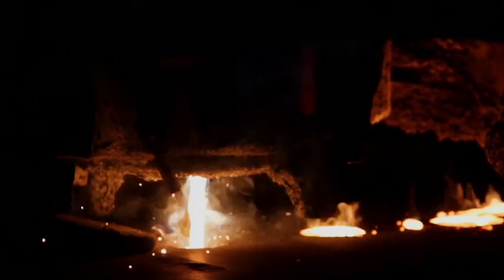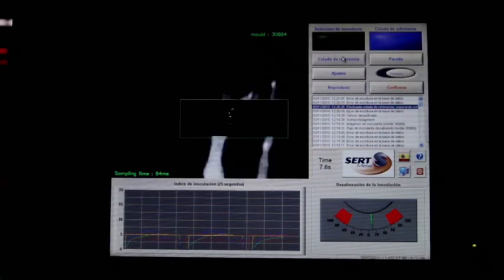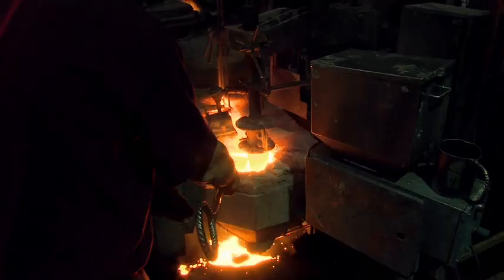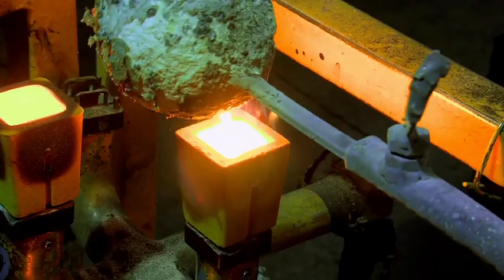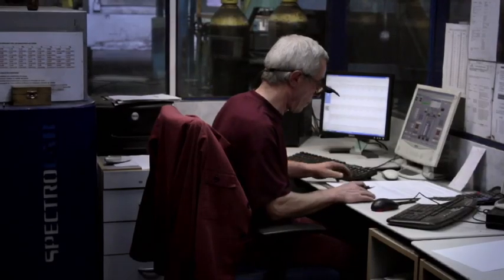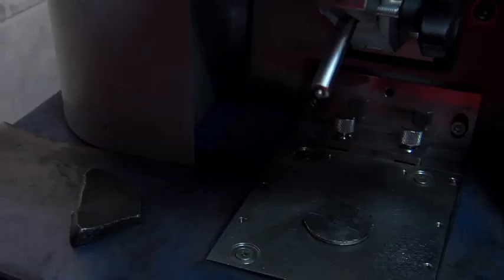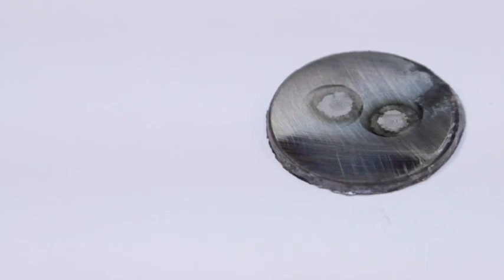As part of this operation, the nodularity of each tap from the furnaces is automatically controlled at the last moment, i.e., when the magnesium is at its lowest. The batches of parts cool down on a 45-meter-long automatic transporter for an hour and a half or 2 hours and then fall into the demolding drum, in which the parts are separated from the sand, which returns to the sand shop closed circuit.